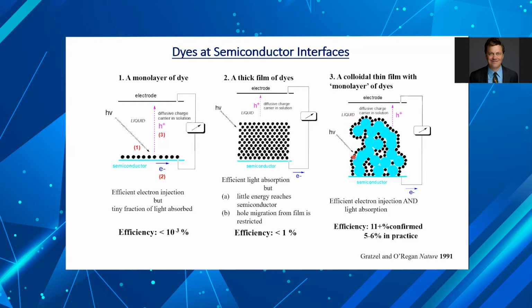And in addition, when an individual dye injects an electron, that oxidized dye now is in an electrolyte. You can submerge the whole film in an electrolyte solution with salt that stabilizes it and prevents those unwanted recombination reactions. And since 1991, the field has advanced. It's now possible to buy from several manufacturers the dyes, the mesoporous thin films, and very quickly you can get into an efficiency range that's 5 to 6%. There are record efficiencies that have been confirmed at the National Renewable Energy Lab that are in excess of 11%. That's more challenging.